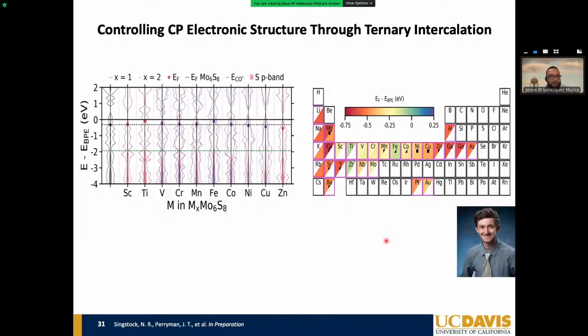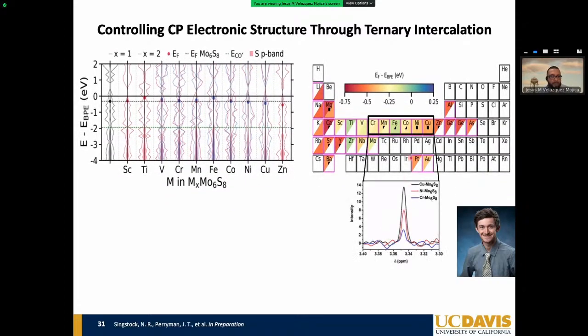We've done a lot of theoretical work with our collaborators in the Boulder group, in the Musgrave group at Boulder. One of the interesting results has been that by changing the intercalant, we are changing the concentration of the production, spoiler alert, of methanol from CO2. What you're seeing here is sort of like a heat map, giving you an idea of how the branching point energy and the Fermi level of these materials can be impacted upon the nature of the intercalant. In other words, we want to intercalate species like potassium, sodium and calcium for us to be able to trigger that ensemble effect that I hypothesized earlier.